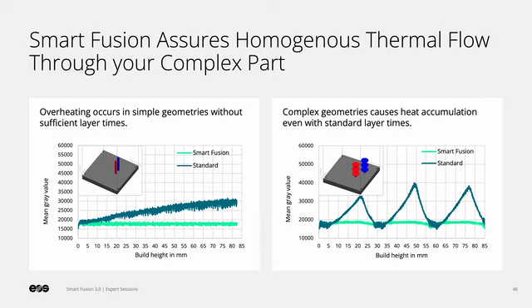Moving away from the application side for a moment and going a bit more into theory, we present two causes of heat accumulation and how Smart Fusion can deal with them on this slide. What is plotted here are the mean OT gray values of an uncontrolled or standard and a Smart Fusion controlled part over the build height. On the left side, we see the results of a set of tall and thin cuboids built on an M290. This represents a very low build job load with short interlayer times, which do not provide enough cooling time from one layer to the next. Over the build height, the part surface temperature, and as a result, the mean gray value in OT, increases. Smart Fusion combats this effect by reducing the laser power accordingly.